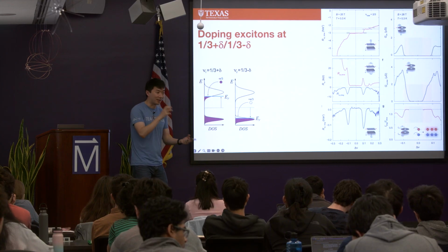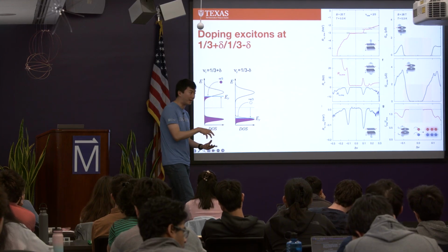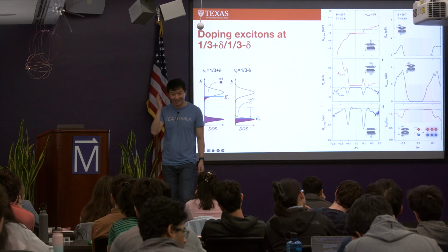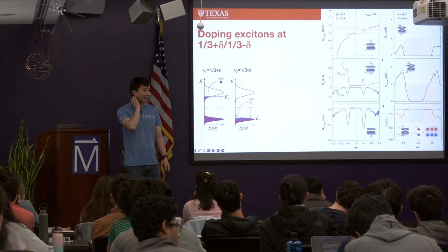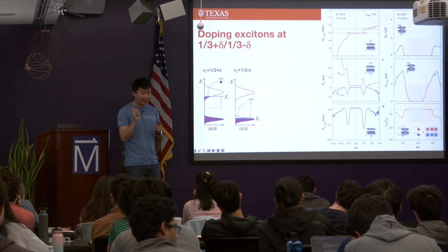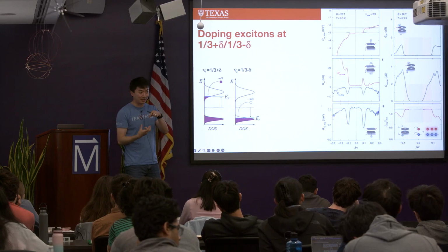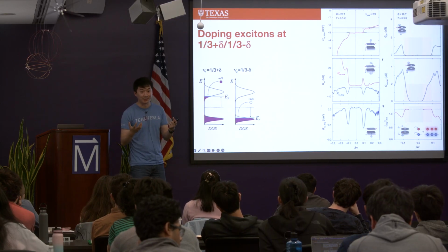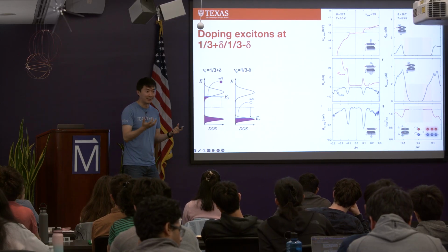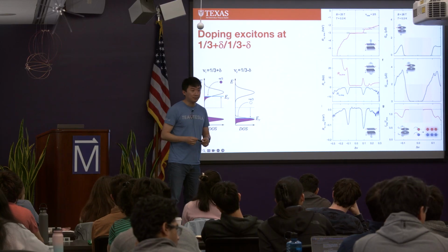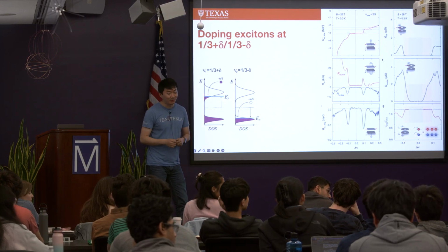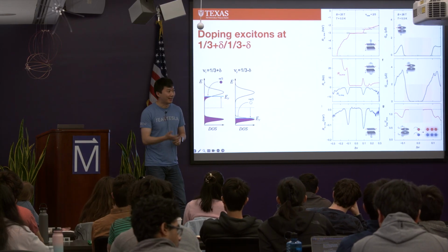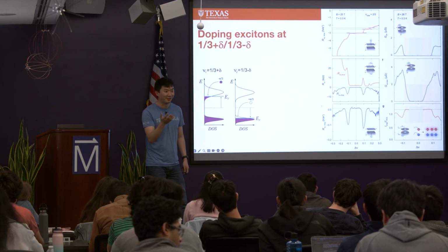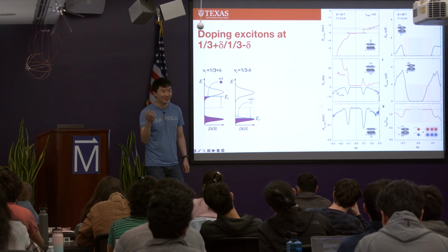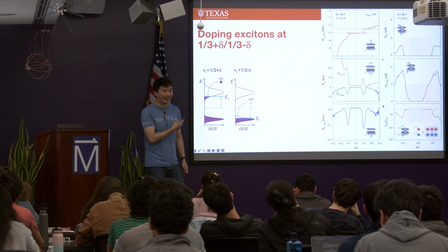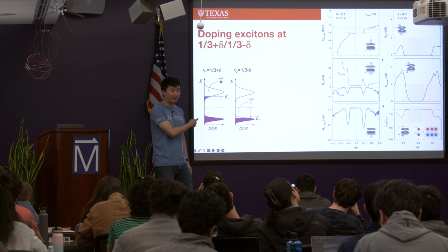But regardless, once they're created, the first thing they do is that they recombine to form exciton. This exciton is interesting because if you think about the braiding statistics, this exciton has fractional braiding statistics. So it's an anyonic exciton. It's not a boson. Right. So I guess Mike Zaletel and Ashvin had a proposal about neutral anyonic superfluid of this type of exciton.